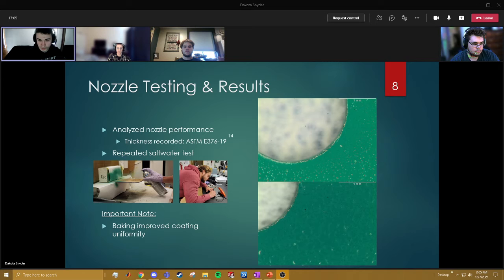The team also decided to bake a second set of samples to see if heat prior to the corrosion experimentation would assist with coating uniformity. These samples were not saltwater tested. The samples were baked for 2 hours at 140 degrees Celsius, which is the operating temperature spec from Scheffler. Nearly every sample in this set displayed significant improvement in coating uniformity and coverage area.